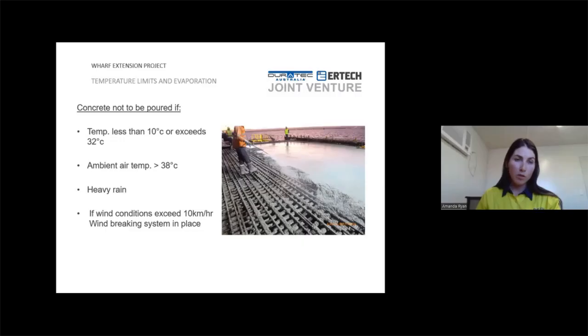So some of the specifications and limits were the concrete cannot be poured if temperature was less than 10 degrees or exceeded 32 degrees Celsius. If the ambient air temperature was greater than 38 degrees, if there was heavy rain, or if wind conditions exceeded 10 kilometers an hour, we had to put a windbreaking system in place, which was the majority of the summer. There always had to be a windbreaking system in place because we were highly exposed out in the ocean. We had some high winds come through there, often getting up to even 50k.